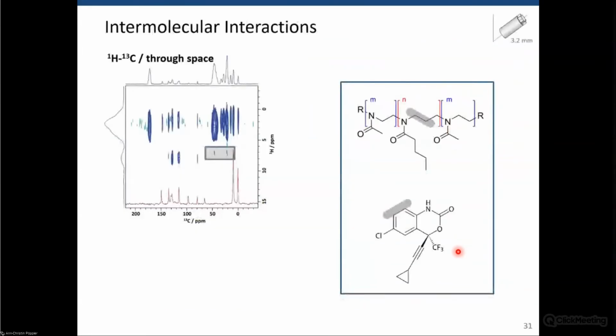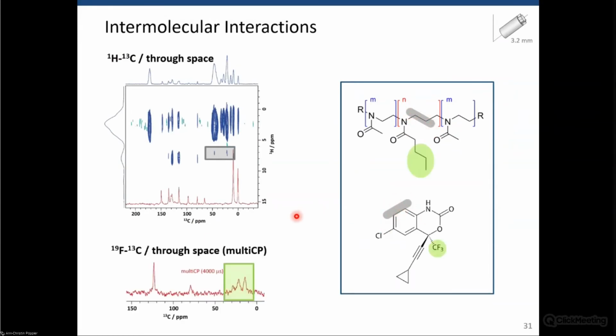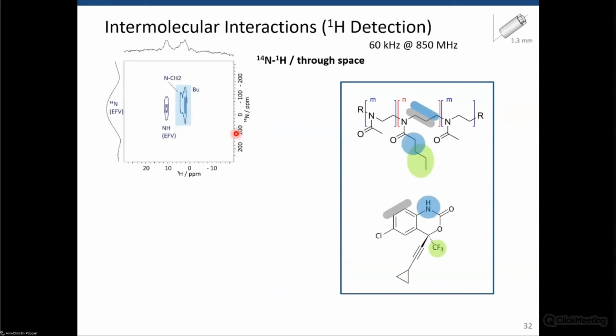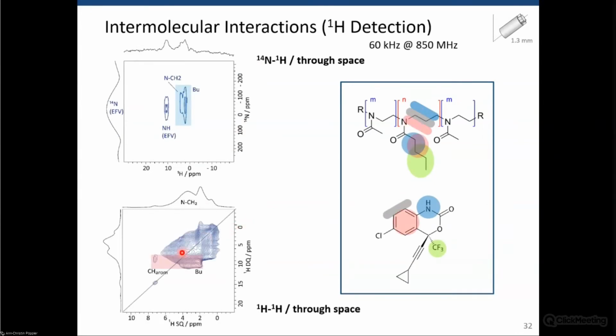So we measured proton-carbon correlations, and then we can see all the colored parts. So gray means carbon is close to proton, backbone, and aromatic ring. Then we can measure fluorine carbon, and we can see the fluorine-containing group is near this butyl chain in the polymer. We can measure nitrogen and proton and detect the blue proximity, and we can measure proton-proton, and we can detect the red proximities. So you can see already that we can start of kind of envisaging where this molecule could sit in the pocket of our polymer, but it's still far away from an actual representation.